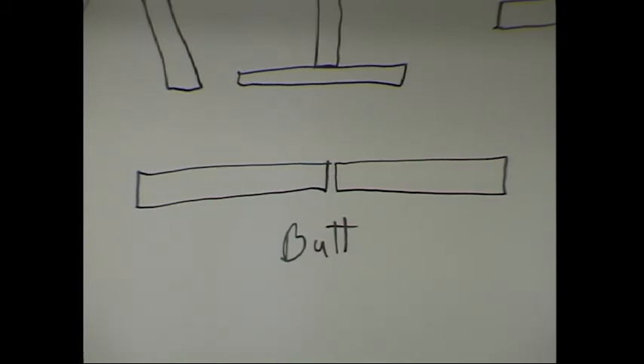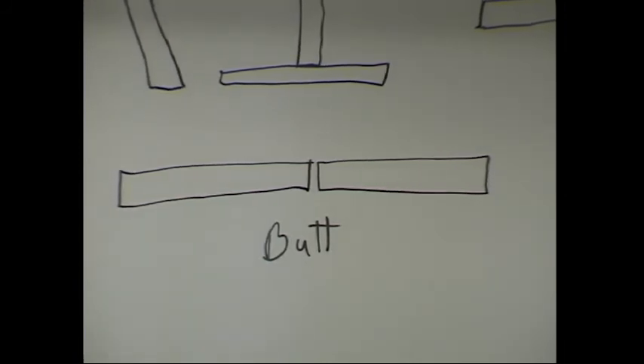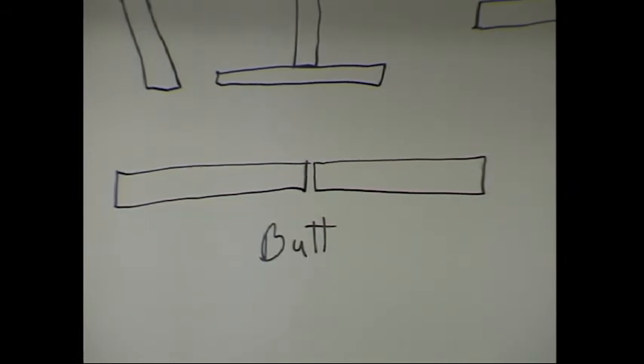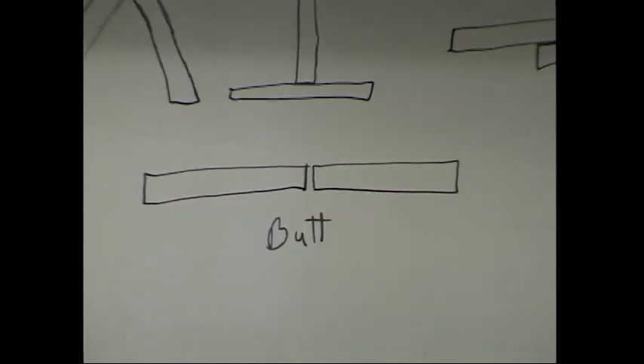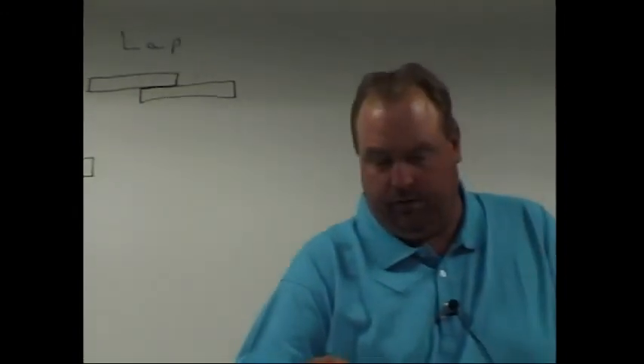When you're welding a butt joint like that, you should always make sure that the joint crack stays in the center of the molten puddle, the center of the bead, and the plate edges are completely fused. The penetration must extend through the root, which means that as you're welding along, you want to pop a little hole in between the joint edges. This is called a keyhole, and it'll open up and round out, and that gives you an indication that your edges are breaking down and fusing completely and that you're pushing filler metal through to the backside. And once again, the reinforcement, in other words the cover on the backside, should not exceed more than about a 16th of an inch above the surface of the base metal.